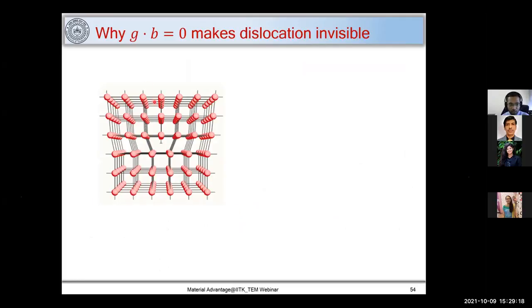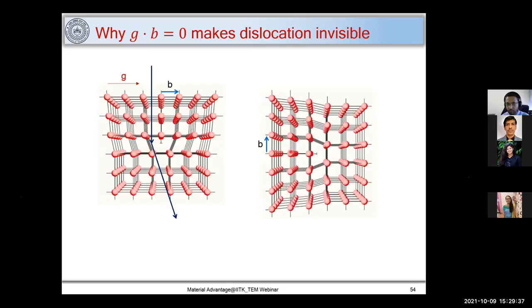I have an edge dislocation here. This is a Burgers vector and this is a G vector. Now, if this is an electron beam which interacts, the planes which are close to the core of the dislocation satisfy Bragg's condition and they diffract. We have seen this scenario. In this case, if I tilt my sample in such a way that all the beams pass through it, there will be no planes which can give me a diffraction contrast. Here is G, and you can see that this B is perpendicular to this G vector, and thus G dot B gives us the invisibility criterion when you talk about dislocation imaging.